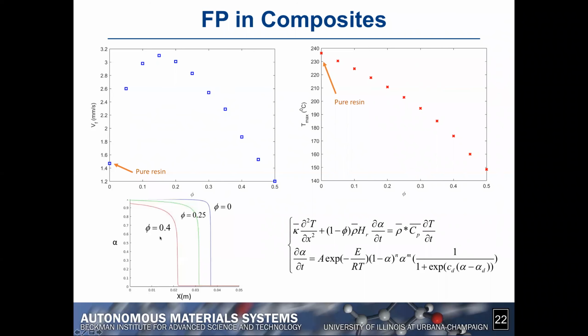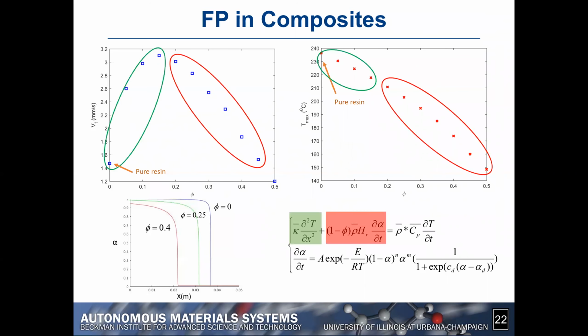And what we observe is that due to the added thermal conductivity created by the fibers, the front becomes less and less sharp, more and more smooth. To try to explain these results, it makes sense that we have 2 regions or 2 parts to the response in terms of the speed of the front. What we observe first as we increase phi is that the term influencing the solution is the one associated with the increased thermal conductivity of the composite. And therefore, since there's an increased thermal conductivity, the front will propagate faster. But at some point, as we increase the fiber volume fraction further, we can see a steady decline in the speed of the front because there's less and less heat generated by the chemical reaction, since we have less and less matrix.